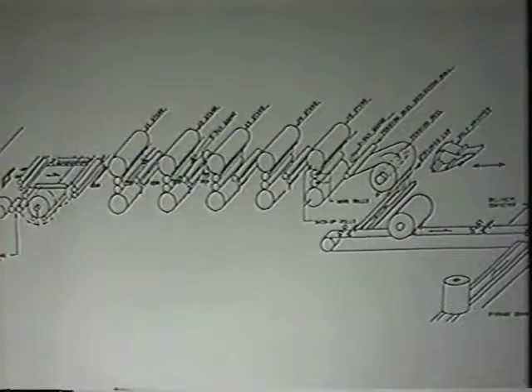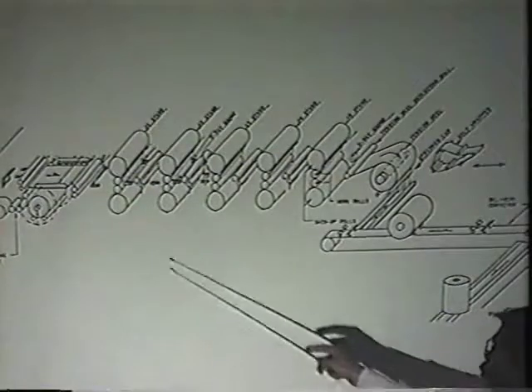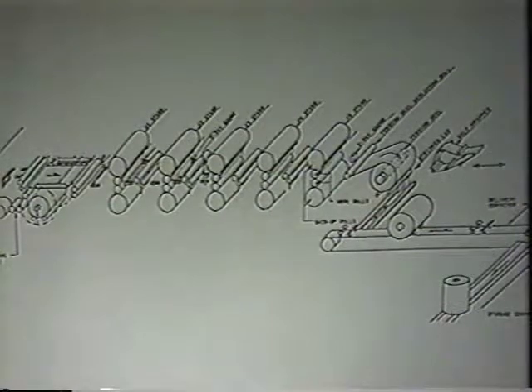In the cold mill, we're actually not putting additional crown into the strip. We're only trying to conform to the crown of the hot band. If we don't conform to that crown, then we'll differentially reduce the strip across the width, and we'll get shape problems. So here we're trying to pretty much match that previously determined profile and not alter it. But if we don't have the rigidity in that mill, as we press down, we will roll the edges more than we will the center and cause problems.